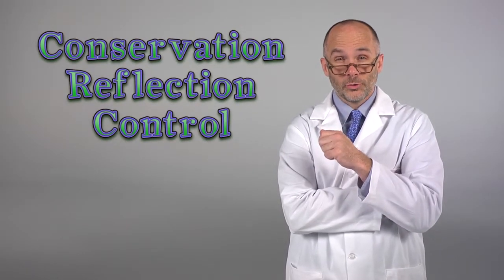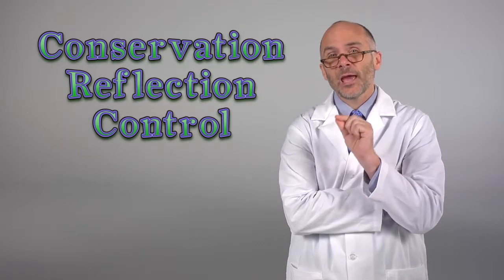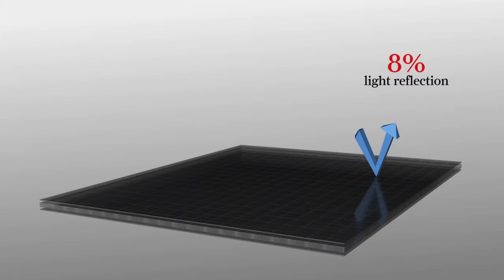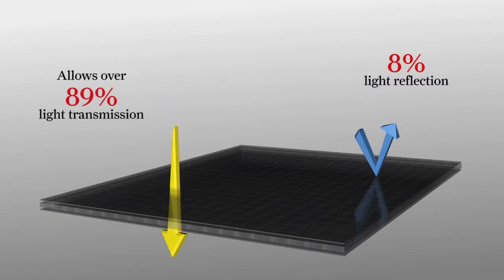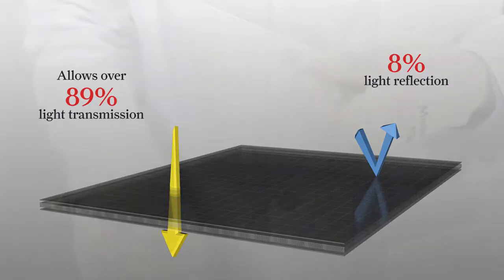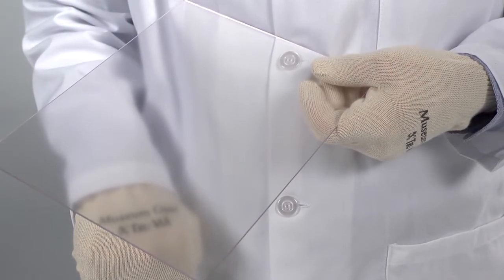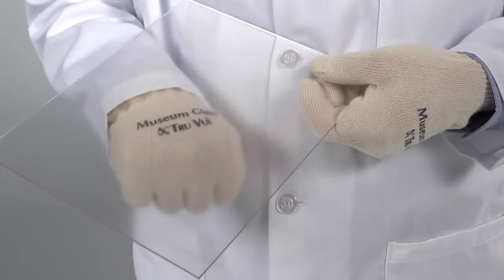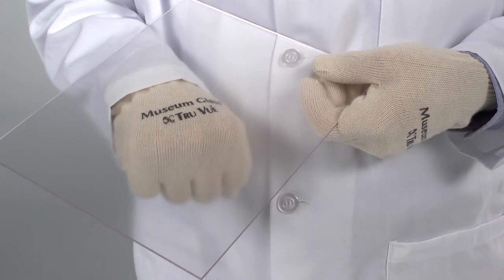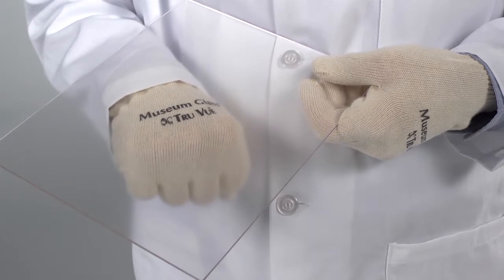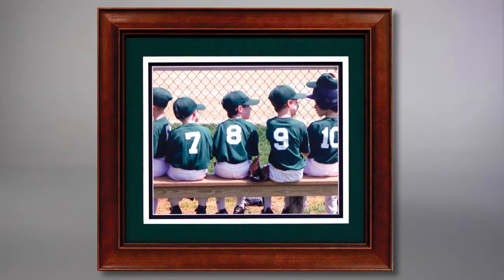Conservation reflection control is a non-glare option that is chemically etched to create a matte-like finish. While 8% of scattered light reduces unwanted glare, 89% of light is transmitted for adequate viewing. The frosted appearance, which is on the side that faces out, minimizes crisp lines and colors, so do not use in shadow boxes. To avoid significant resolution loss, conservation reflection control should not be used if the art is to be more than 1/8 of an inch from the glazing.